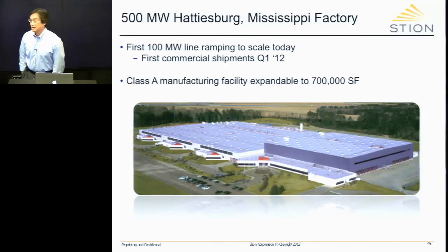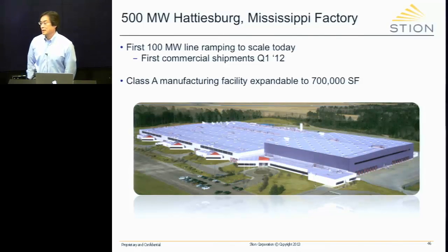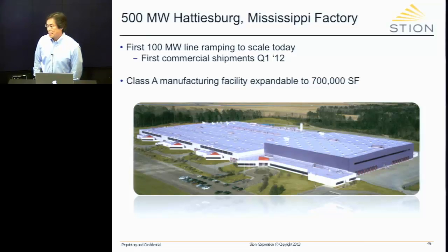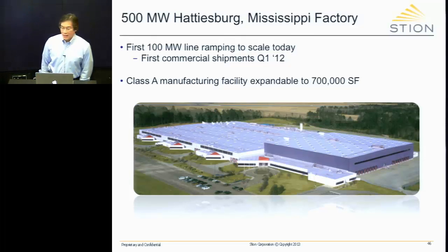If I'm not mistaken, usually solar cells heat through the bottom. You add an extra layer of glass, which is a very low thermal conductivity material, and most of your power is from the top cell. Do you see significant thermal issues because of that extra thermal resistance in series? Actually, that's a great question, because we were worried about that as well. We modeled that, and it turns out that the combination of the breakdown efficiencies presents no problem to us. So in other words, we just use those 2 pieces of glass, and it is perfectly fine. But we were worried as well.